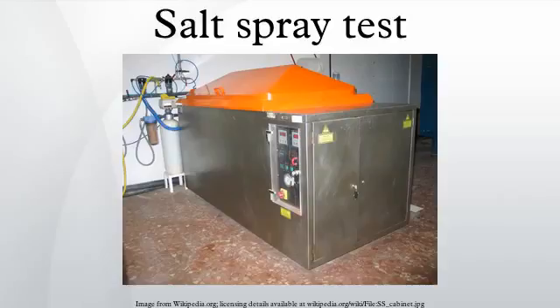ASTM G85 Annex A2: acidified salt fog test. This test can be used to test the relative resistance to corrosion of aluminium alloys when exposed to a changing climate of acetic acid salt spray, followed by air drying, followed by high humidity, all at an elevated temperature. This test is also referred to as a MASTMAASIS test.